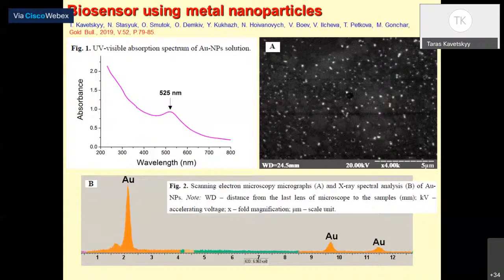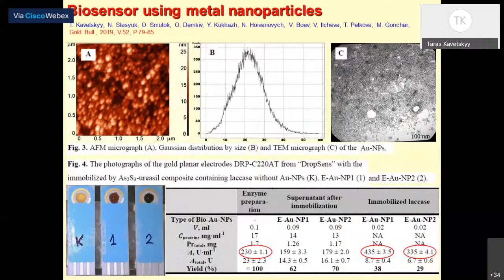Here we prove the concept that incorporation of gold nanoparticles should increase the sensitivity of biosensors, and we add gold nanoparticles to our ureasil matrix. Here is the AFM and SEM analysis and DLS analysis of gold nanoparticles. We estimated the size of nanoparticles to be around 20 nanometers.